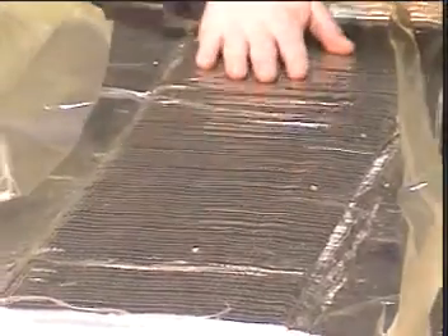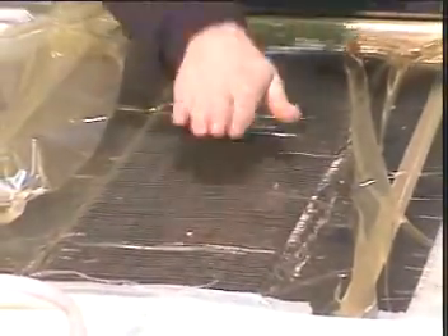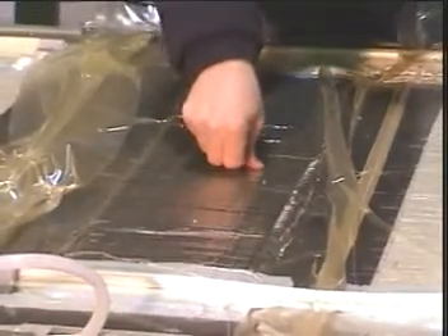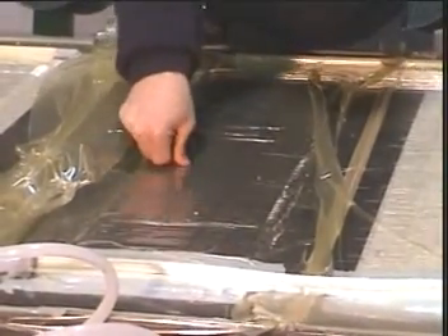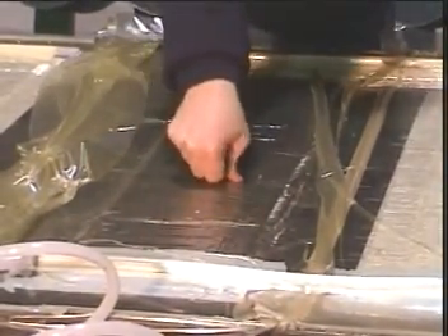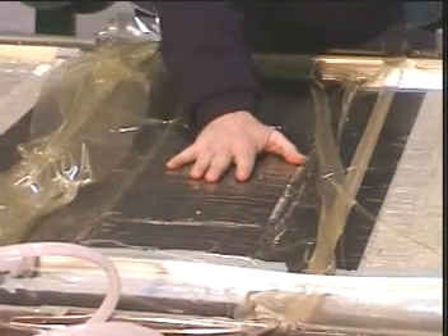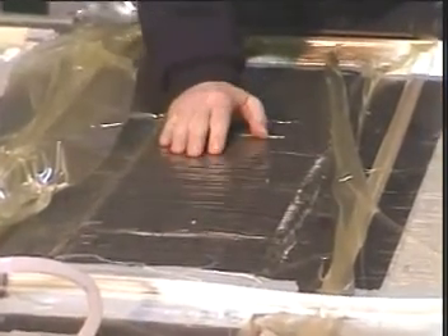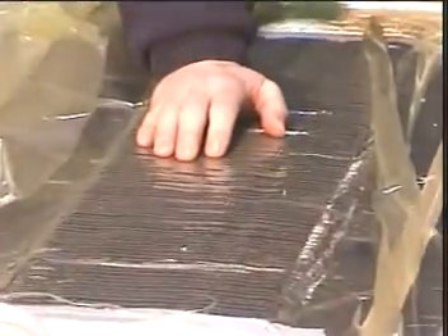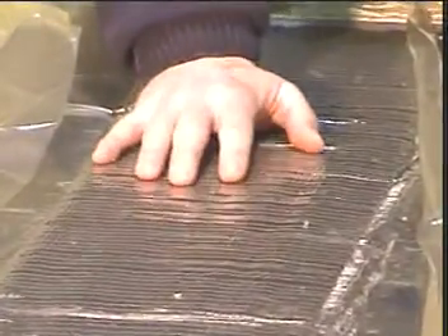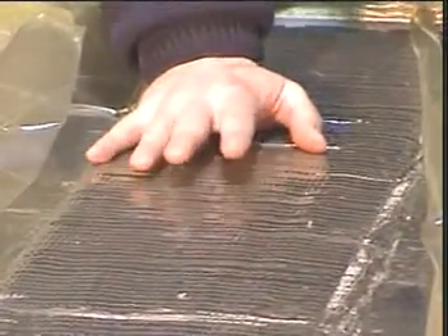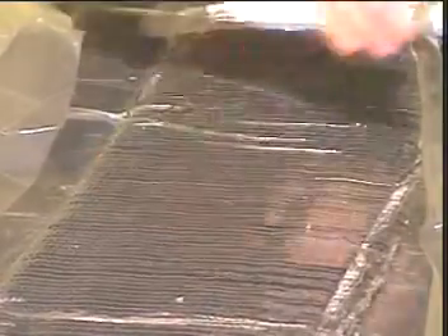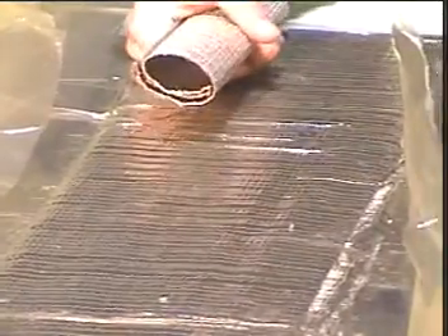So anyway, here's the carbon panel. You can see the wrinkles in the fiber. You can see the waviness. And again, as I push on this, maybe you can see that. The thicker the laminate, when it's under vacuum, you can actually dent the laminate. That denting, in a big part, where you're walking on it sometimes to make sure the bag doesn't have any leaks, that denting causes further wrinkling in the preform. It can be a real problem. Let's move over to the glass panel.